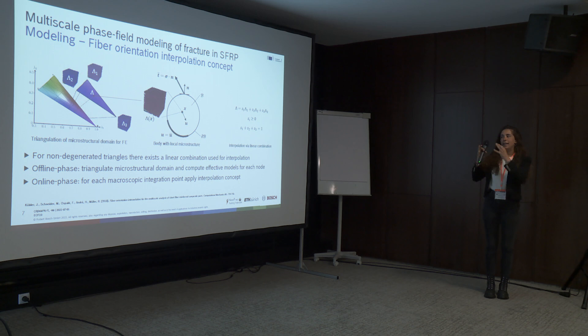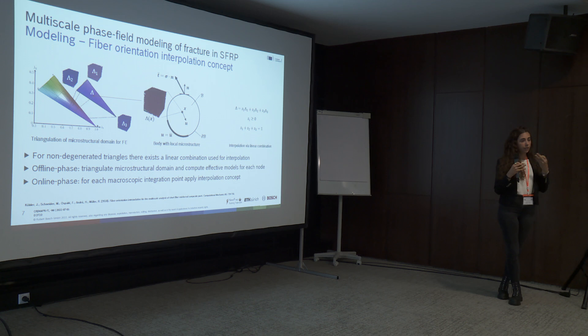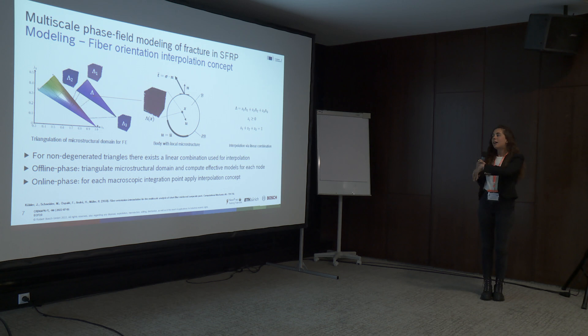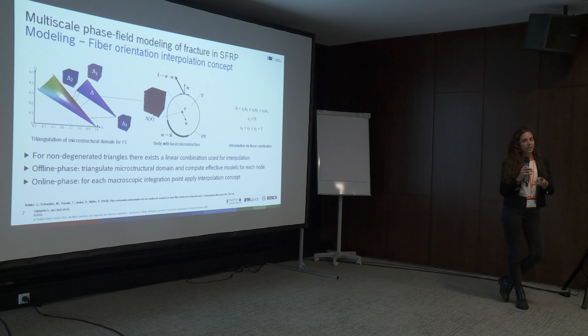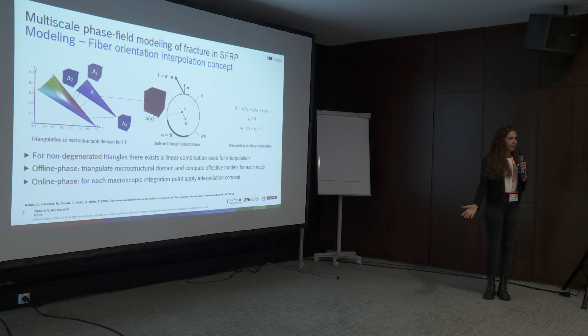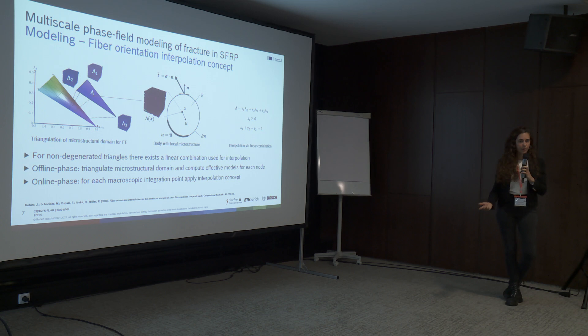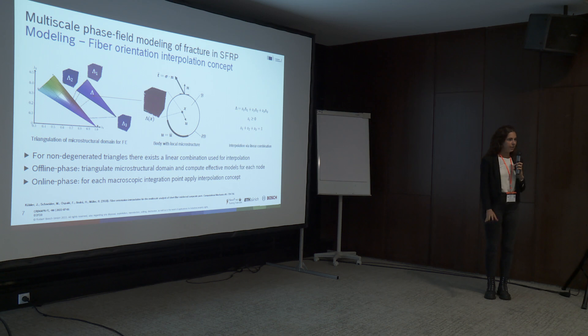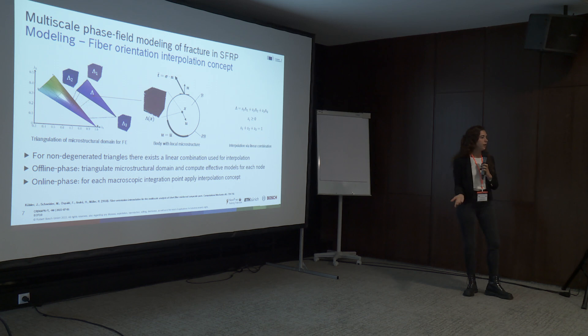At each integration point I can link to an orientation distribution characterized by the fiber orientation tensor, and locate the real microstructure within the triangle. To promote accuracy, I am discretizing this triangle: in an offline phase I create many microstructures virtually using a fiber generation tool, then perform micromechanical computations to characterize them mechanically.